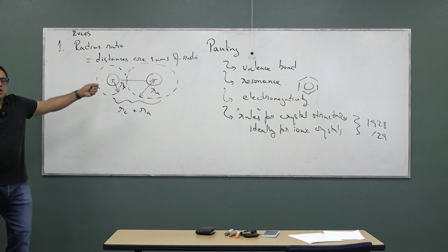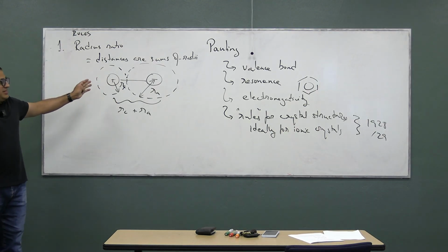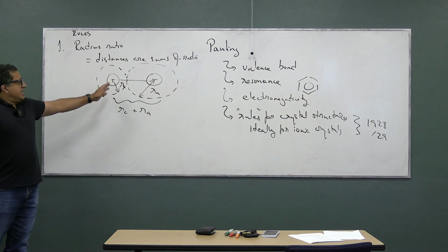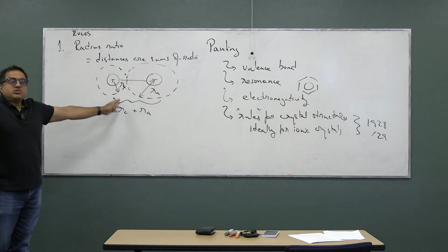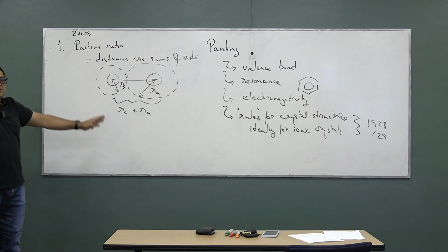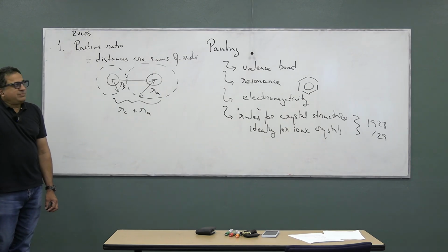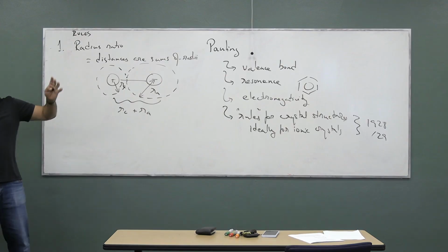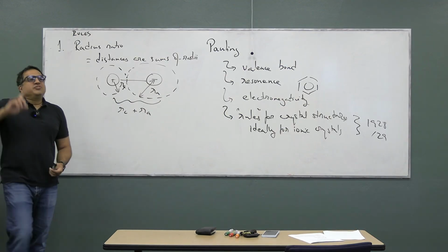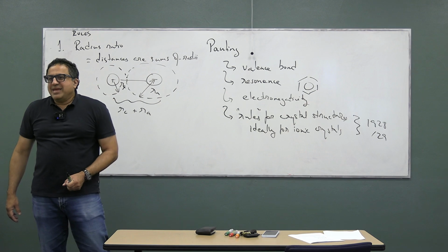Okay? And this is not only obvious, it's actually circular, because the way we assign distances is we measure the total distance experimentally, and then we apportion the distance, and we say this much comes from the cation and this much comes from the anion. Right? Does that make sense? And I can go through the history of how this was first done, because if you have a whole bunch of distances, you have to fix at least one in order to get the other distances. Yes?